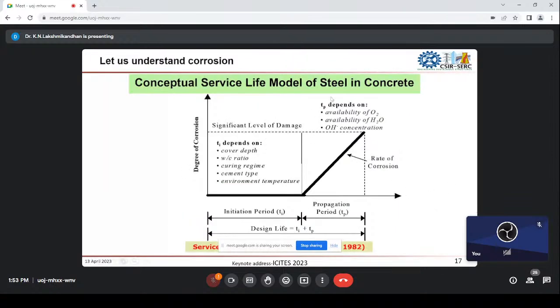So this is the typical representation of the life model for steel in concrete. Normally this is the initiation period. Before initiation of corrosion, the steel is strong enough. Once corrosion is initiated, it is very fast and accelerated. Generally this depends on the availability of oxygen, the availability of water, and the OH concentration. If the calcium hydroxide concentration is very high, then the corrosion will be controlled. If there is a reduction of the calcium hydroxide concentration, then faster corrosion happens.